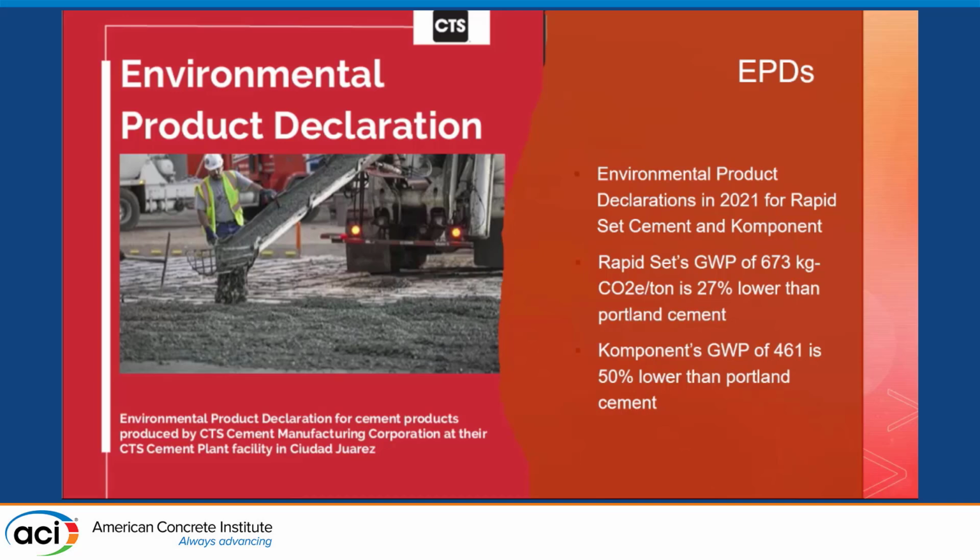And just to finish the parenthesis, a really hot topic, right? The global warming potential impact of these materials, of these alternative cements. There is a certified EPD value for BCSA, which is around 70% of the GWP of Portland cement. And for Komponent, which is our shrinkage-compensating cement, the value is a lot lower. Yes, the Komponent is blended with Portland, so we will need to do the math. But that's also work that we do because we believe it's part of the real-world use of the material, and we need to adapt and we need to be ready for the new tendencies.